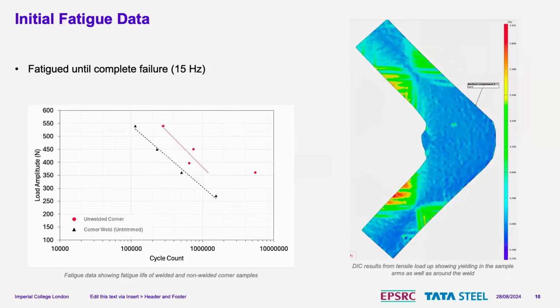Going on to my data then. So this is the DIC from that. This is a little bit after the sample has started to yield. I use that yield point as my absolute max. Do not go over this during the fatigue tests. And you can see, it's not quite high enough resolution, but we do just about see the stress concentration on the sides of the weld in the DIC data. But what we see over here is we have our unwelded corners in red and our welded ones in black. And so there is a decrease in life from the corner weld.